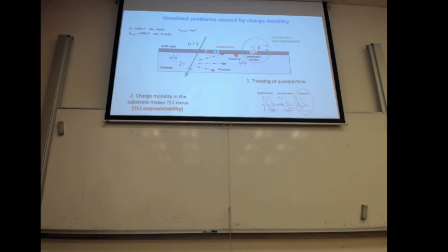But now we have also started to fill all the gaps in the picture, right? Because I told you, because of this spin, we have formation of traps. And then we know that these electrons go very far, so they can be trapped. And once they are trapped, the question is, can they form two-level systems, or are they just trapped quasi-particles? We saw that we could solve this problem with the gap engineering, although this problem highlights the fact that we don't understand very well at all what the relaxation is in thin aluminum.